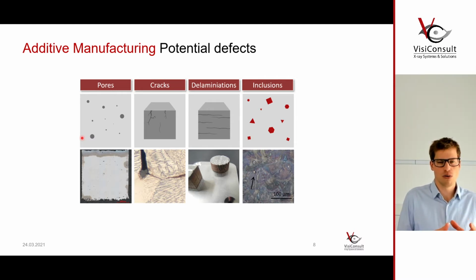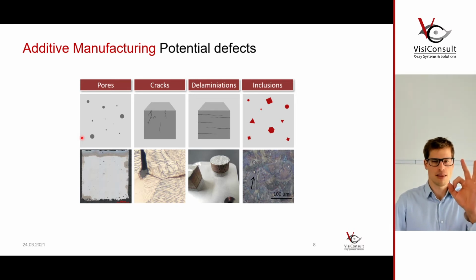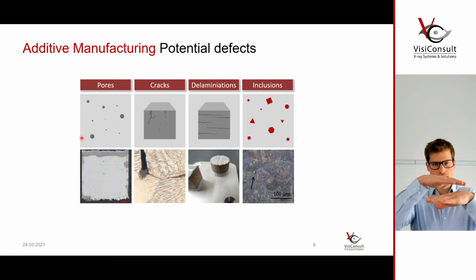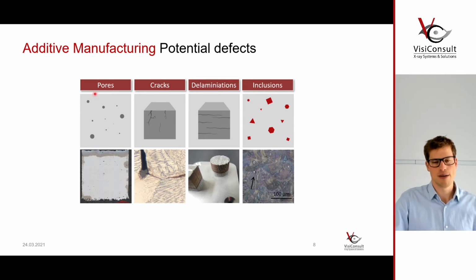We kind of know the spectrum of defects and we know the implications for the real part. With additive manufacturing, that's different, because when you have a round porosity with casting, that is one thing. But if you have, let's say, a flat porosity, because we have a layer by layer built up in additive manufacturing, the implications for cyclic loading and stress-related aspects are quite different, because a round sphere is very unlikely to act as a crack kernel. On the other hand, if you have something that has edges and corners, it can crack pretty easily under tension.